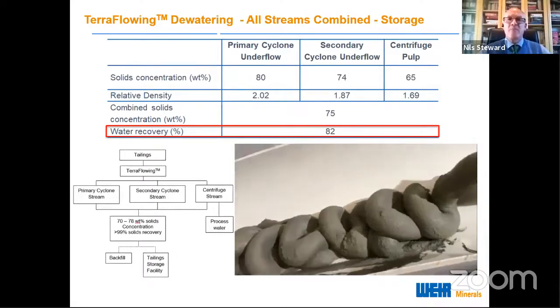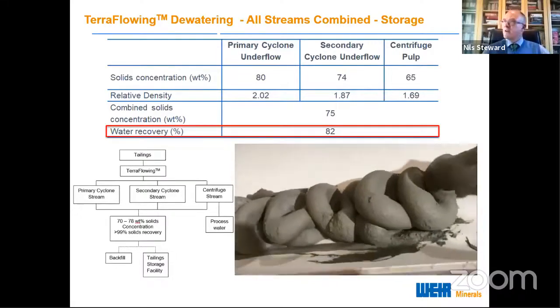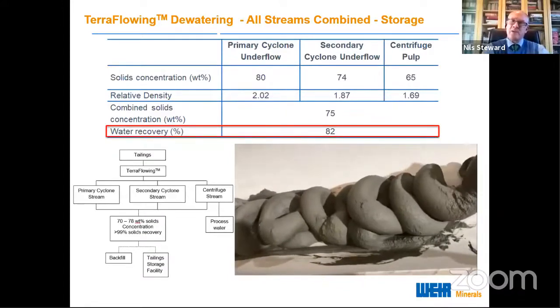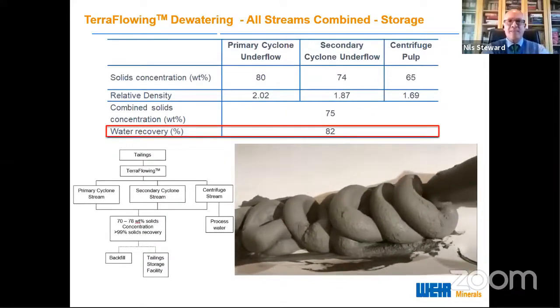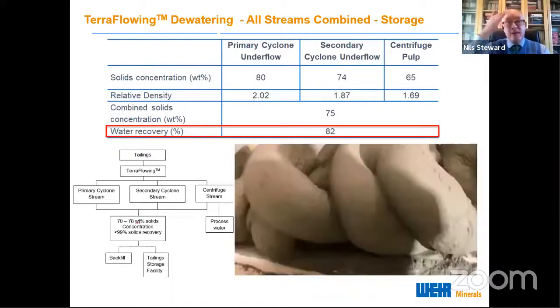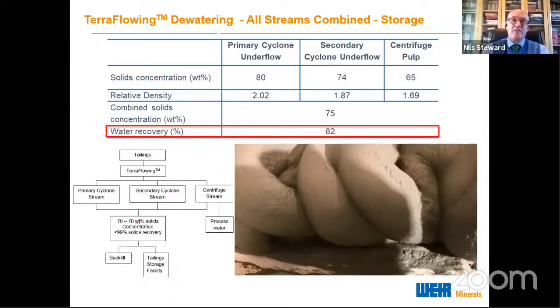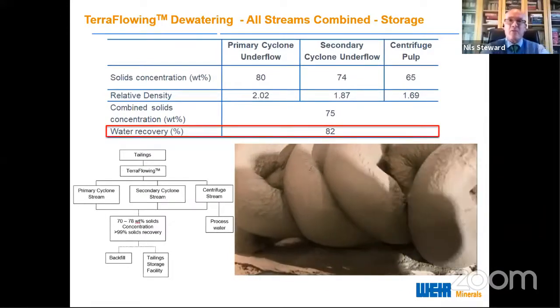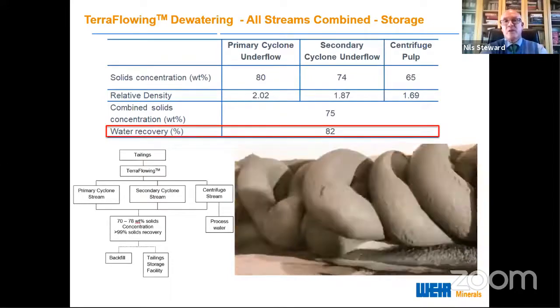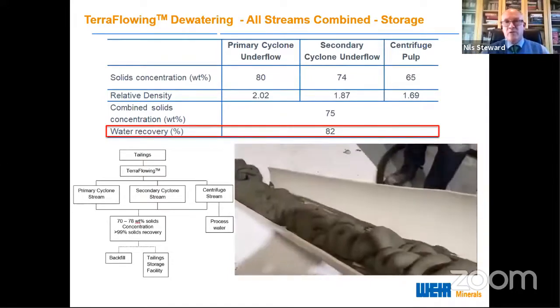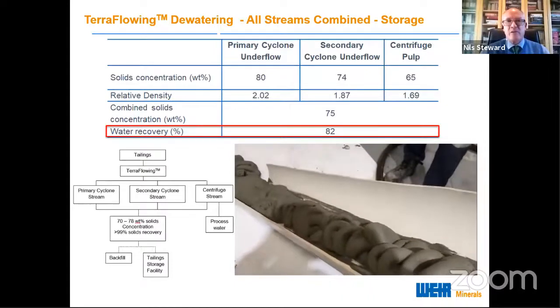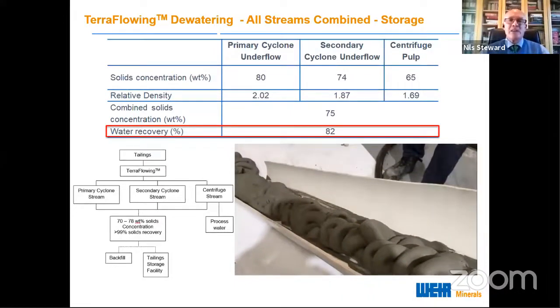And if we combine those, we recover around 82% of the total water in the tailings, assuming that the tailings came out of a thickener at around 35 weight% solids. So, sorry, out of the met plant at around 38 weight% solids. So what we're producing by combining all 3 of them is a very stackable product. And we're able to produce that at anywhere from 70 to 78 weight% solids.